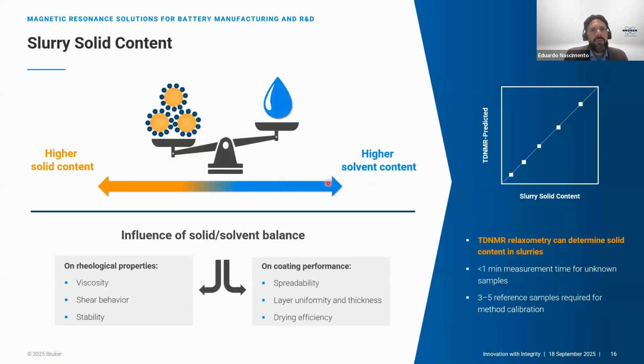So the last application I will talk about here: I said that you can correlate the TD-NMR information with other parameters. For example, we normally correlate that with rheological properties like viscosity, shear behavior, and stability. And we have been using that to calculate the solid fraction content of slurries as well. Provided that you can calibrate the system, you need just 3 to 5 reference samples; you calibrate the system once, and then you don't need to do that anymore, unless you are changing recipes or working with different types of slurries and so on. But once you have a calibration curve, you can get your results quite fast. So for everything that I said, for the homogeneity, for the recipe deviation, and for your slurry fraction calculation, the measurement time is around 30 seconds, and you get all these results. So it's quite fast.